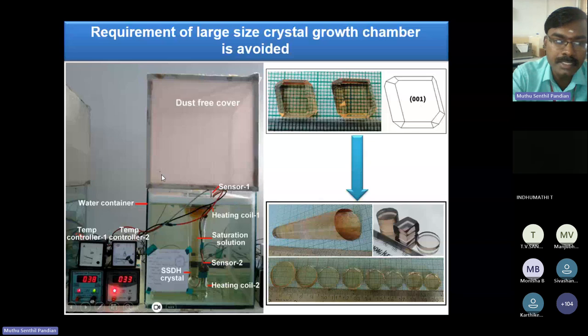So using this SR setup, we cut the crystal using a fine wire ablation frame at its C direction, this portion, and we mount it at the bottom of the glass ampoule, and we pour the solution, and we grow this much large size, 9 cm length and 2.5 cm diameter, of the same SSDH single crystal by this same SR method.